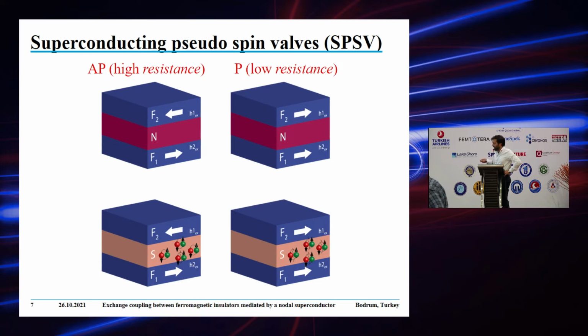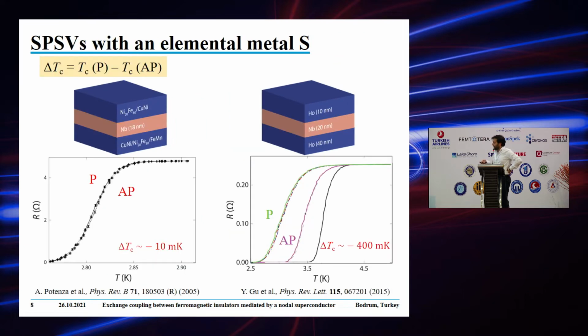So you get a weaker superconductivity compared to the other case, where the exchange fields point in opposite directions. In that case you expect a more robust superconductivity. Weaker or more robust superconductivity means that here you have a lower TC compared to the other situation, where you have a higher TC. As I mentioned before, this is for a spin singlet superconductor. If you have a spin triplet superconductor, things can change, but we will focus just on spin singlet pseudo spin valves.